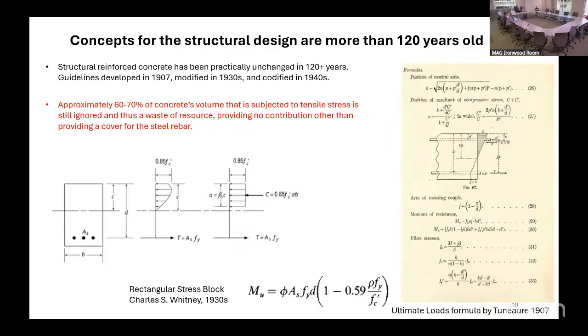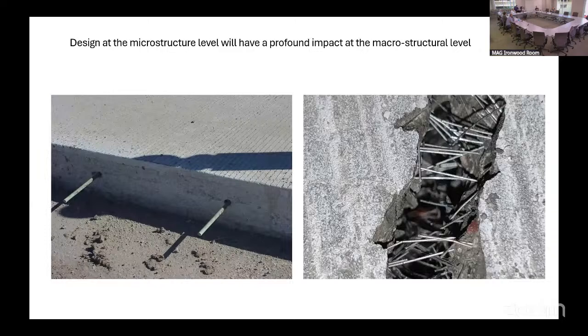So what we are saying, next slide, is that if instead of rebars that are, for example, here on a pavement, transferring the load only from a shear point of view, we use fibers. The fibers are crack arresters. They won't even allow the crack to propagate. They make it difficult for the crack to propagate. So for cracking, you need energy, and that energy is sucked up by the fibers, by friction, by pullout, and by all these mechanisms. They hold the cracks together so that your aggregates now are providing the interlock. So it is a symbiotic relationship. You don't just put one rebar thinking from a macroscopic point of view that rebar is going to carry all the load. Before the load is able to come to it, it's going to be carried by the fibers across. And this is what I've dedicated my career to.